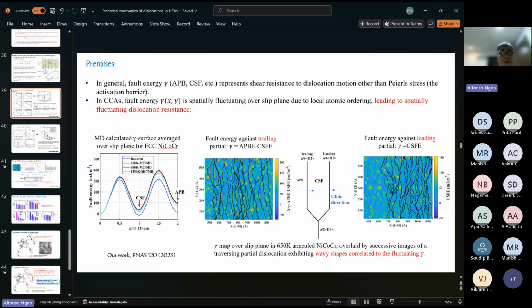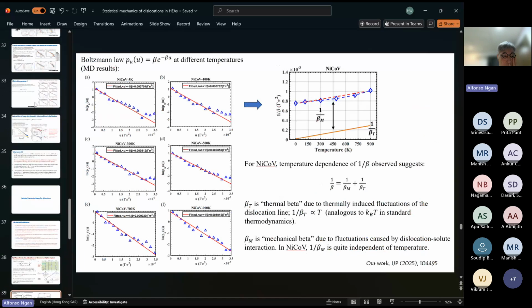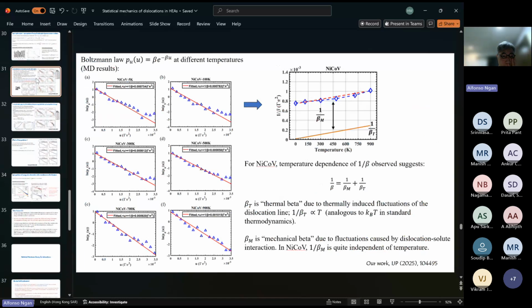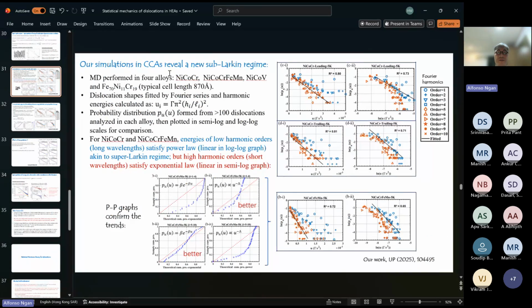So let me go back to that slide, if I can find it. We looked at 4 alloys. For the first 2, the typical cell length in the MD simulation was 800 something, 900 angstroms. Within that cell length, half of the harmonics would fall into the super-Larkin, and roughly half would fall into the sub-Larkin. So we do have the transition at the midpoint, roughly 400, 500 angstroms for the transition length scale.